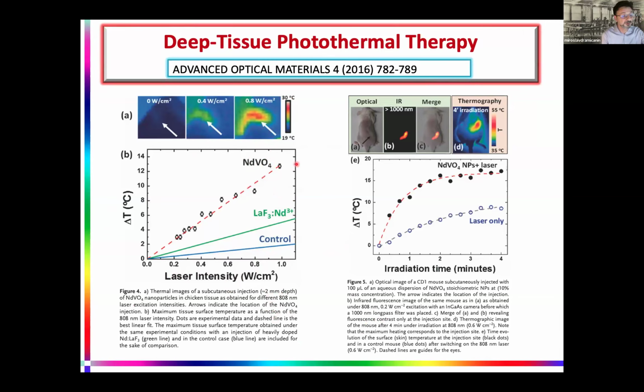So these nanoparticles are 2 millimeters below the tissue surface, and then we are taking thermal imaging of the tissue on the surface, and we can clearly see the heating of the tissue. So this means that we are able to use these nanoparticles as nanoheaters inside the biological environment. And here on the right side, you can see the results of measurements when we introduce these nanoparticles into the cancer of a living mouse. On the left, you can see the optical image. Here is the infrared image, and you can clearly see luminescence, because it's infrared, it can penetrate outside of the body. And this is the merge of these two images, where you can see the mouse with the illuminated cancer.